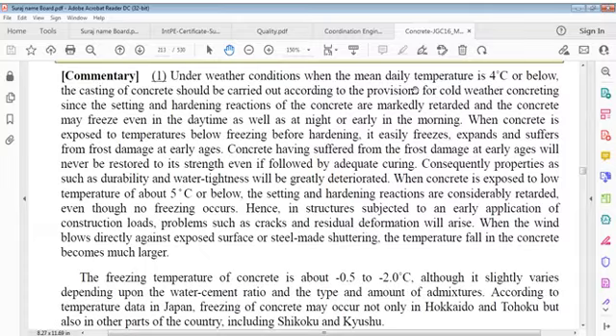When concrete is exposed to low temperature of about 5 degrees Celsius or below, setting and hardening reactions are considerably retarded, even though no freezing occurs. Hence, in structures subject to an early application of construction loads, problems such as cracks and residual deformation arise. When wind blows directly against exposed surface or steel shuttering, temperature fall in concrete becomes much larger.